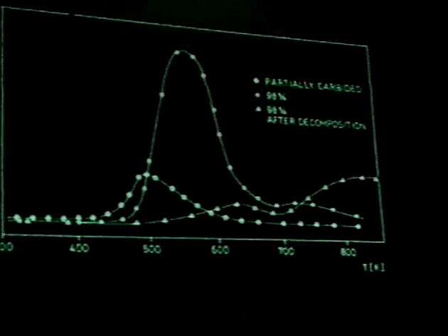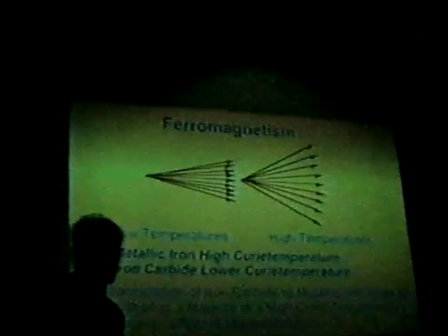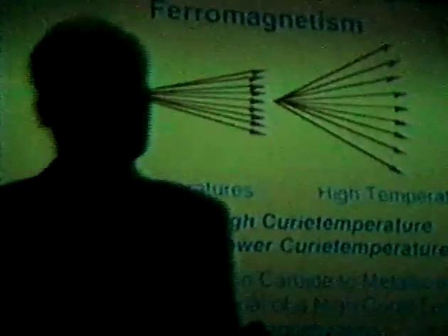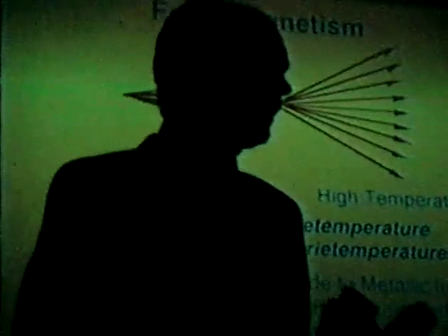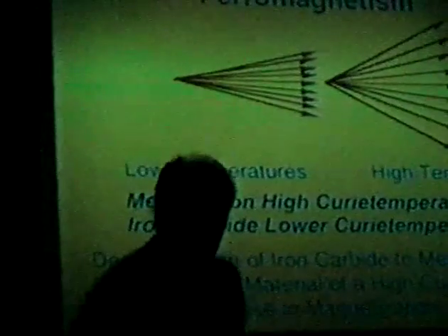That is from the temperature programmed hydrogenation measurement. Now we are considering the magnetic measurement. We are using the Curie temperature because I now want to go over to iron, and whereas nickel carbide is not ferromagnetic, the difficulty is that the iron carbides are still ferromagnetic. So what we are using is the Curie temperature.